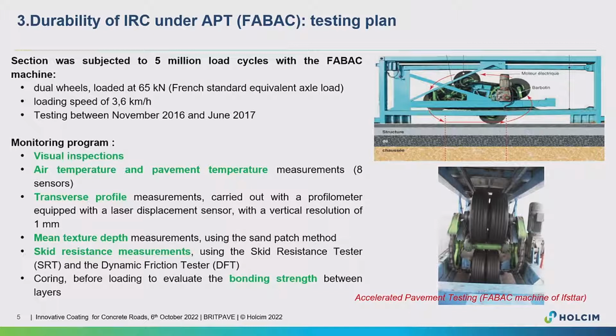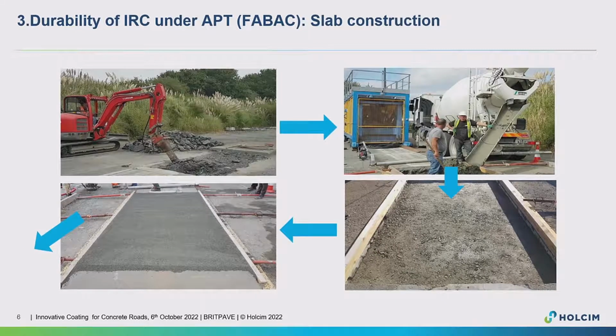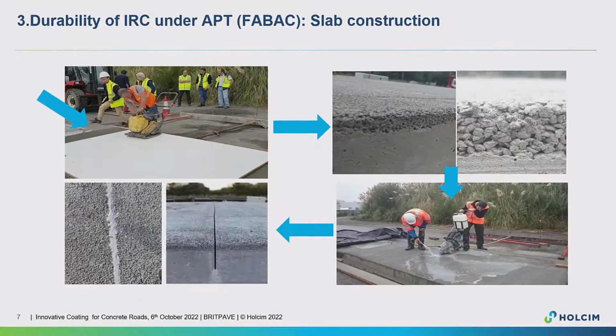So the monitoring program is classical, with visual inspections, air temperature and pavement temperature survey, transverse profile measurements, mean texture depth measurements, and skid resistance measurement by the skid resistance tester, the British pendulum, and the dynamic friction tester. And for sure, we cored before the loading to check the bonding between layers. So some pictures of our slab construction. We sawed exclusively two small joints, just filled by a polymer, just to create the weakest points in this slab.